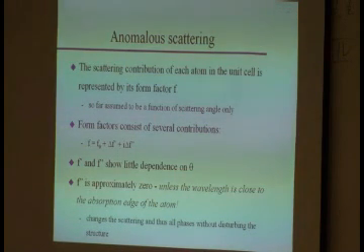However, if you remember when we first introduced it, we did say it also depends on the wavelength. And we didn't really talk about that in detail. What it really is, your F has several contributions. It has an F0 that simply depends on your atom, and then it has these components, F prime and F double prime. So your F should really be properly written as F0 plus delta F prime plus i delta F double prime. Ooh, another complex quantity.